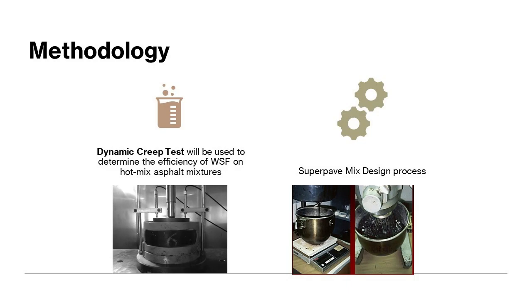A dynamic creep test will be used to determine the efficiency of WSF, waste steel fiber, in hot mix asphalt mixture at the UTHM Transportation and Highway Laboratory. The Superpave mix design process comprises several steps, the first of which is material preparation, which is divided into several stages. This study will utilize the Superpave gyratory compactor to prepare HMA samples to evaluate mechanical and volumetric properties as per AASHTO T312.